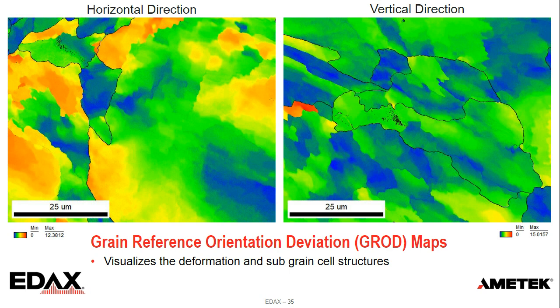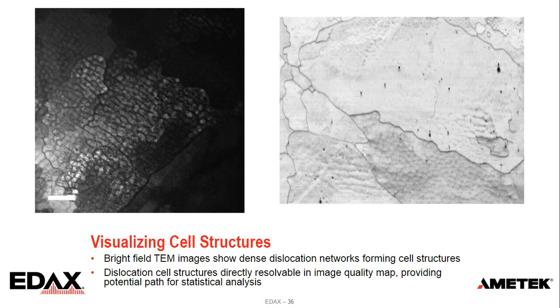Within the grains, you can start to see this kind of cell subgrain structure, a fingerprint of the deformation. And we can compare this to TEM results. This is a bright field TEM image on the left, and you can see that cell structure pretty clearly. On the right is the image quality map from one of those higher magnification images. You can see we actually can detect some of that cell structure in the bottom just through the image quality as well, which I thought was really interesting.